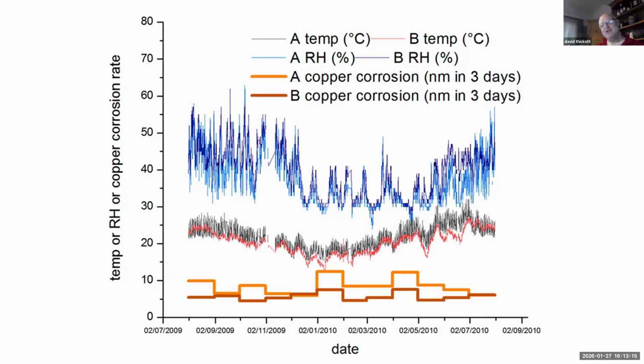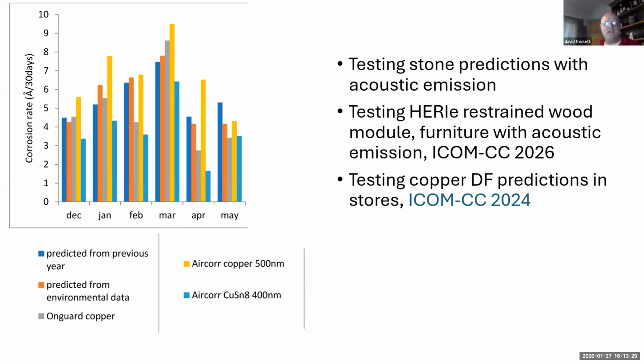Caitlin's already mentioned some healthy skepticism on what you need to know. We've done this work, and we then want to test how good it is. So we did measurements again during the loan, and we compared them with what we predicted from the previous year's data. It's a different year's data, so things are a bit different. The most important one on there is probably the grey bar for the copper, the on-guard, which is how we developed the damage functions.